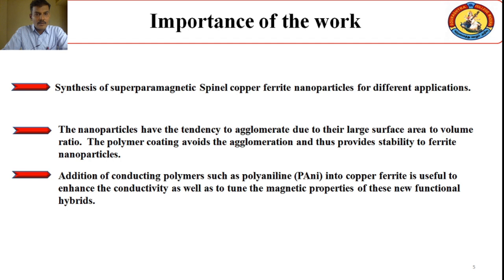In this presentation, we are going to synthesize superparamagnetic spinel copper ferrite nanoparticles. The important issue is the tendency of this magnetic nanoparticle to easily agglomerate with each other. That is mainly because of its dipole-dipole interaction and surface to volume ratio. So to avoid the agglomeration, we must keep some coating on the surface of superparamagnetic nanoparticles. Here we are trying to coat a polyaniline nanopolymer on the surface of the copper ferrite element. Successfully we have synthesized the core-shell nanocomposites, and the addition of polyaniline creates high conducting behavior. Meanwhile, that is very useful to tune the magnetic behavior of the ferrite element.